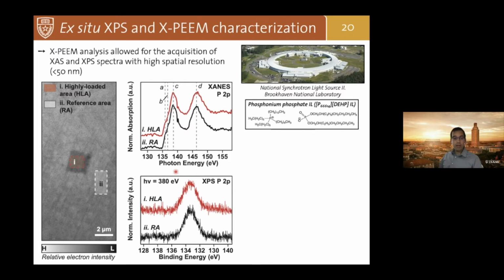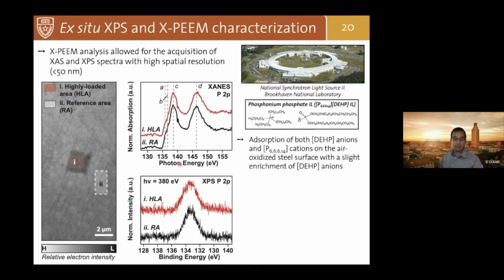But basically, we were able to acquire X-ray absorption and X-ray photoemission spectra inside the region scanned at high load and outside. And as you can guess, there is not any significant difference. I'm not going to talk extensively about what all these spectra are. The main take-home message is that there is not any significant difference. And careful XPS analysis that we did shows that there are both cations and anions adsorbed on the surface, with a slight enrichment of the anions on the surface.